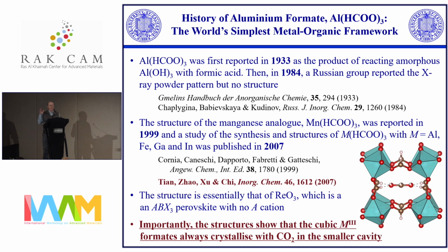But at that point, in a sense, they were not MOFs. And what all of these materials, the Gatteschi ones and the Tian ones, had in common is that when you crystallized them out and did the crystal structure, they actually have carbon dioxide in the cavity, as you can see there. And I noticed this, and when we were doing the review, I looked at this paper by Tian, and I thought, well, that's an interesting thing. And the title of the paper was Templating of Aluminum Formates by Carbon Dioxide.